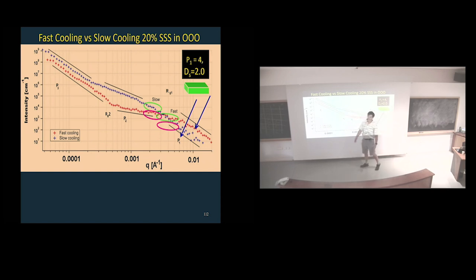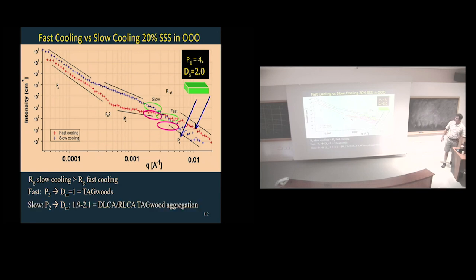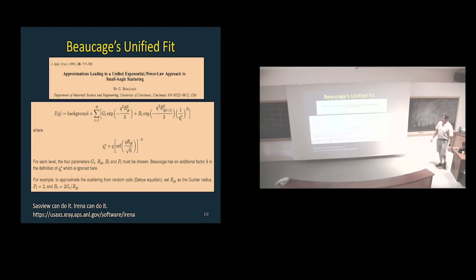This slope was a mass fractal. And then we got a second Rg2, which was 1 to 2 microns, what you see under the microscope. And we're like, beer time. You know, and then up here, this P3, we had no idea what it was. It can be surface, it can be mass, depending on whatever it wants to do. So you can imagine, right? Cluster aggregation. You can talk about all kinds of things. And if you need to know, I put it here.